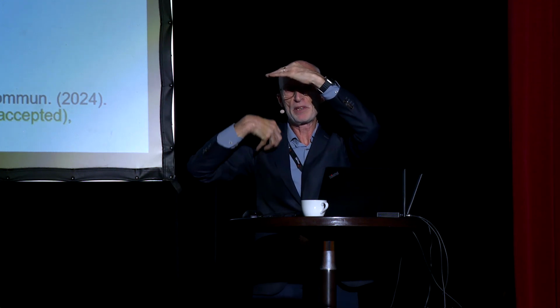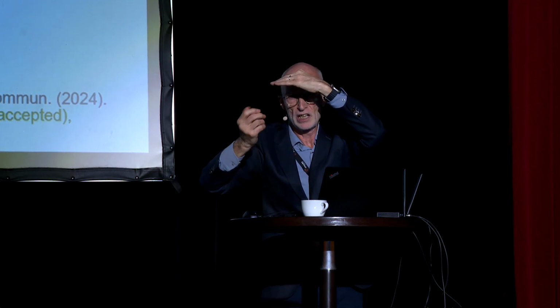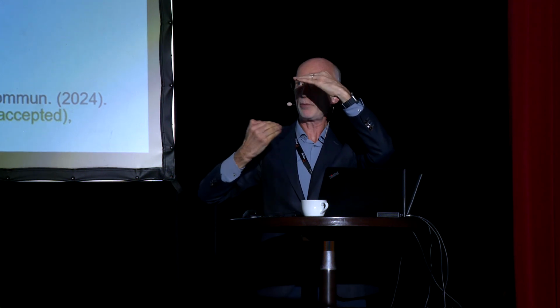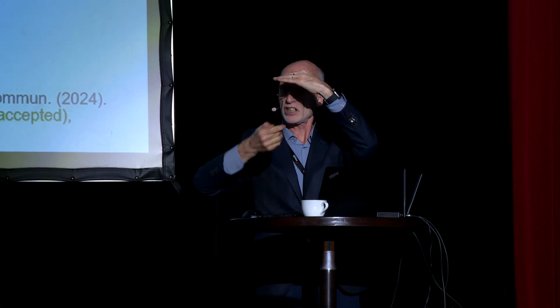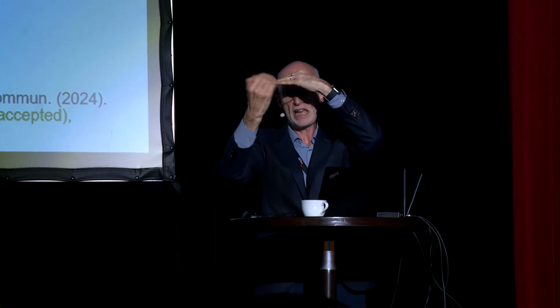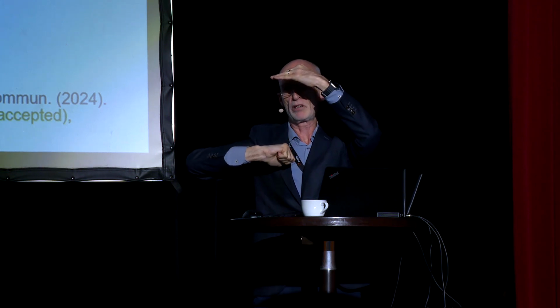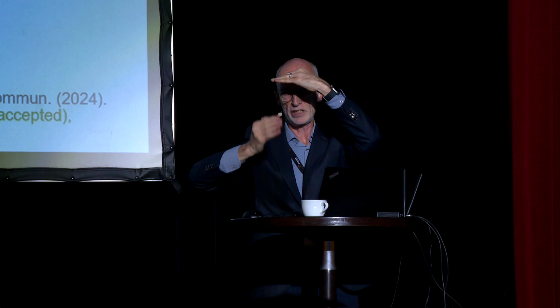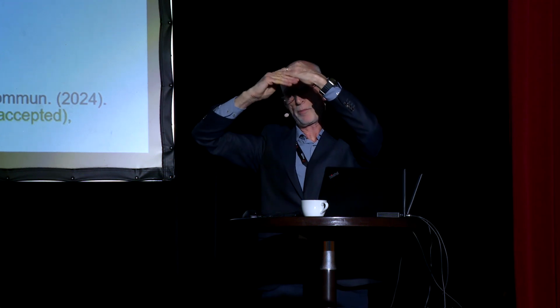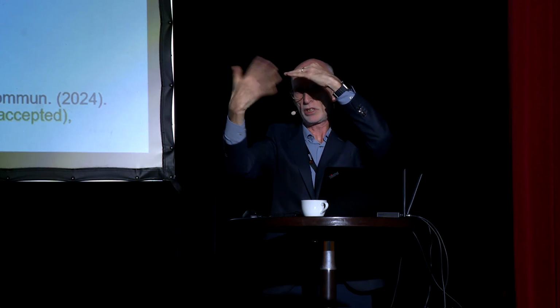So I showed you a conventional tunnel junction, cobalt-iron, MgO, cobalt-iron. In fact, there's 10 other layers to make it useful. You have to make each layer from a synthetic antiferromagnet, non-trivial. Here you have a system where you automatically have an antiferromagnet. So these types of new Van der Waals antiferromagnets, or even more interesting, the chiral antiferromagnets, where if you can extract spin polarized current, would be super interesting technologically. They would be the most technologically relevant materials, the chiral antiferromagnets. Single layer would be simpler to make, in principle.